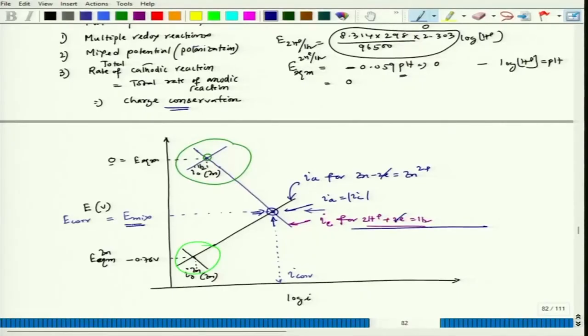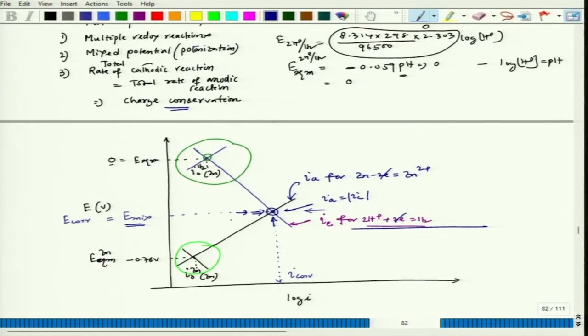Now, the system would try to maintain this E corr or E mix. So, now if we want to find out what should be my polarization, or from which reference potential I should see the polarization, that reference potential should be E mix. In case of a single redox process, we used E equilibrium as the reference potential for seeing the polarization. Okay? But here, my polarization would be considered with reference to E mix or E corr. So, this is the potential which we have to consider from the beginning, and then from that particular potential we have to see whether we can go up or down.